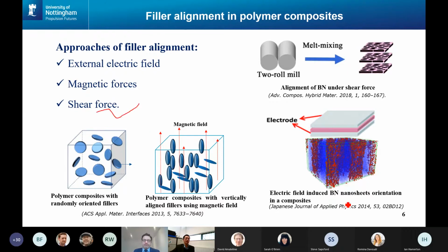If we use an electric field or magnetic field, under this kind of external force, we have to make the filler itself electrical field active or magnetic field active. Then we can do something there, but the problem is that when we introduce additional ions or additional particles, that will affect its electrical resistance. So another way is to use the shear force method. In the shear force method, the most popular approach is melting the polymer, or dissolving or dispersing these particles inside the polymer, then doing extrusion together. That can help the alignment of the filler, but one thing is the contact between the fillers is difficult to control.